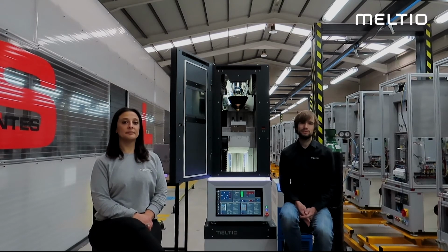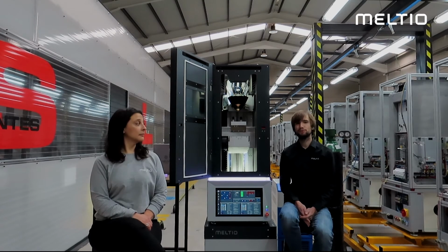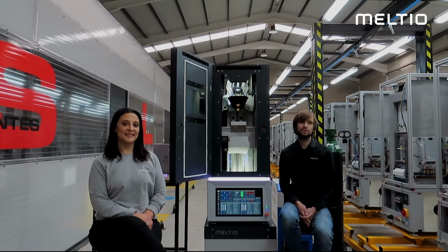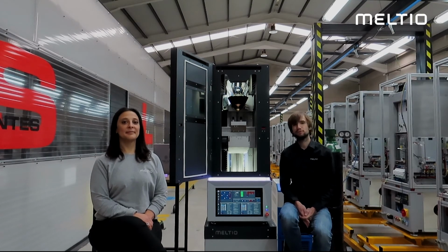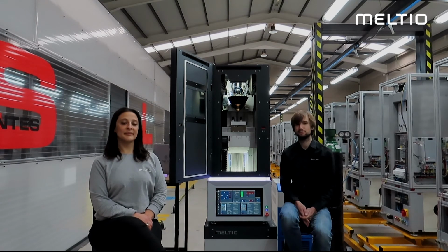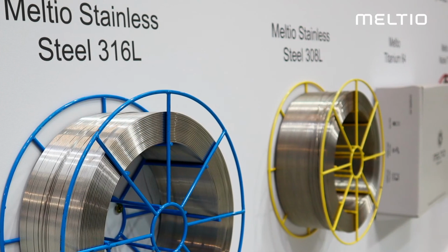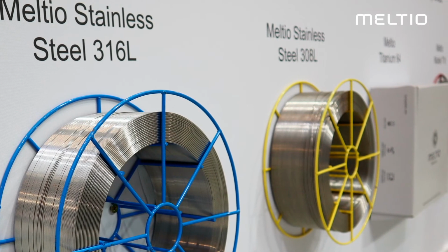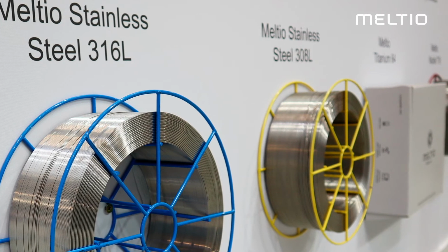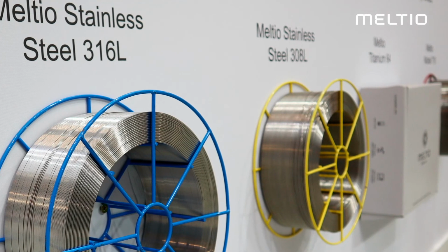The M450 can process materials between 0.8 and 1.2 millimeters in diameter, that's approximately 0.035 inches to 0.045 inches for imperial units. Currently, Meltio's pioneering process is compatible with most stainless steels, mild steels, tool steels, titanium alloys, and nickel alloys. And in addition to that, Invar, cobalt chrome alloys, and precious metals like gold have shown great results in customer-led projects. Meltio's current offering of materials includes stainless steel 308, stainless steel 316, mild steel ER70S, titanium 64, and of course nickel 718.